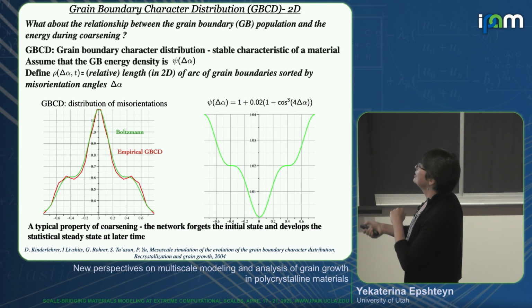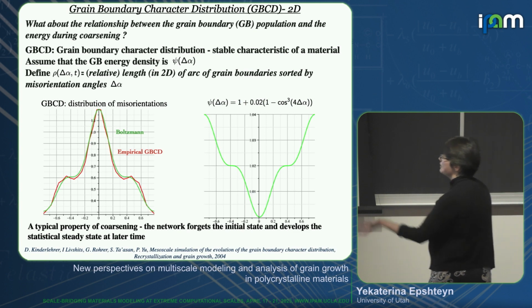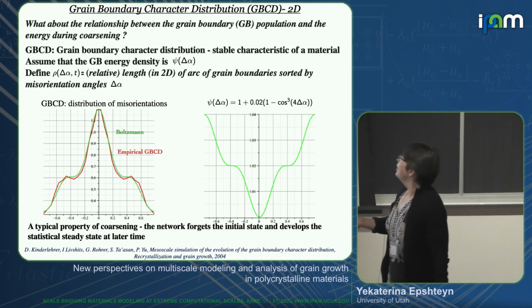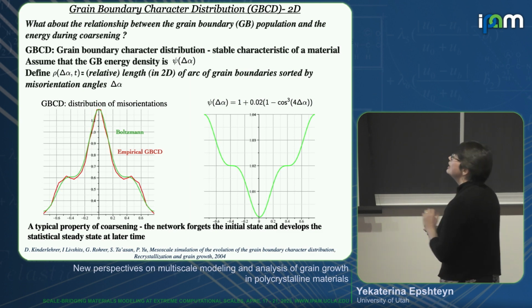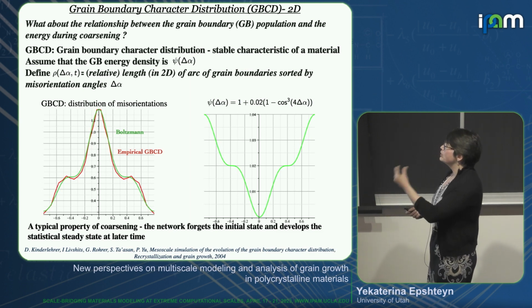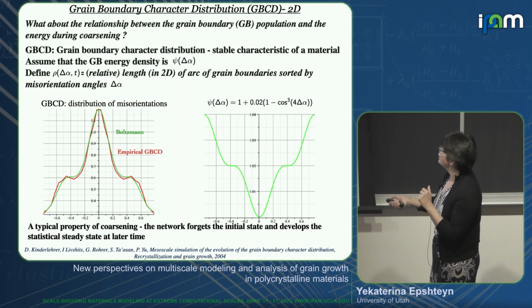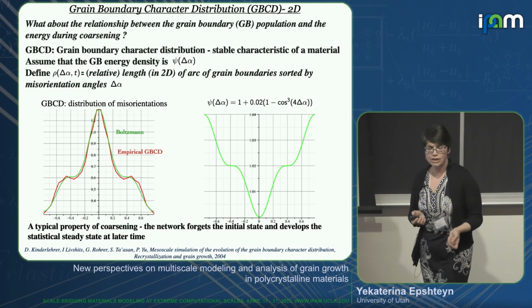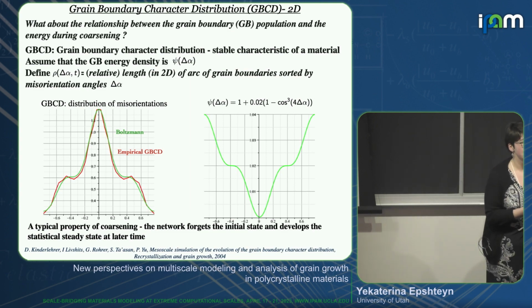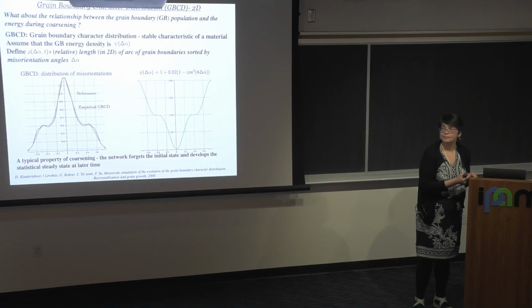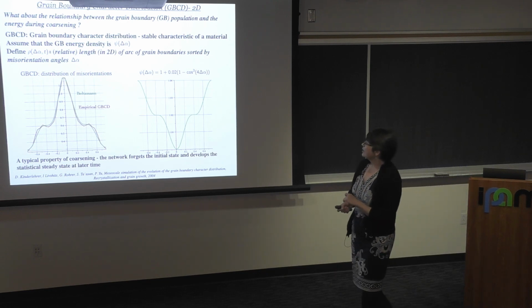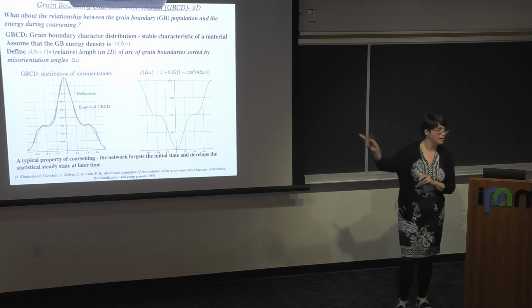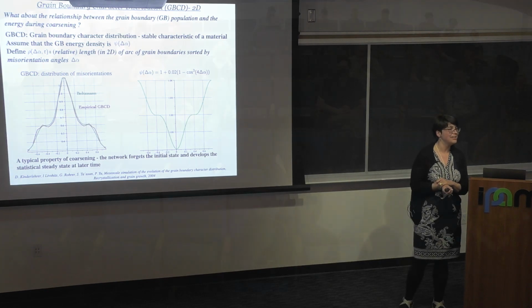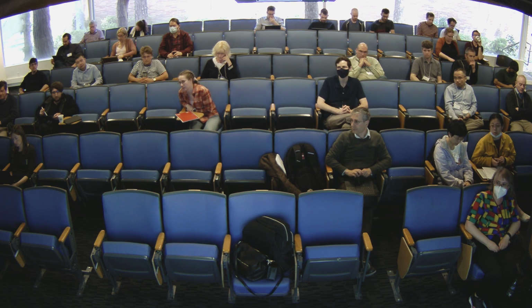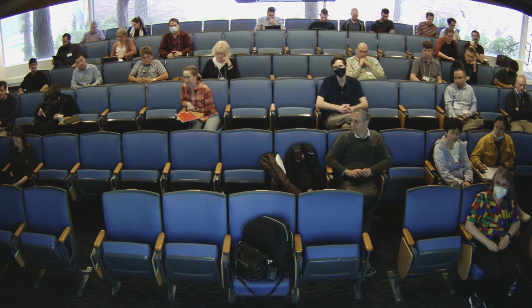so basically we expect, and that expectation is now confirmed by simulations, experiments, and theory, that these statistics will make a connection and give us information about the relation between grain boundary population and grain boundary energies. Excuse me, where is this sigma 3, sigma 11 on this graph on the right? Here it's a simplified model. So in this model I don't. But on the next graph I will show which comes from experiments with the simulations.